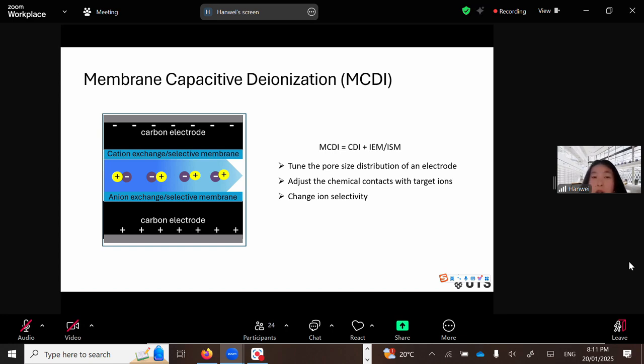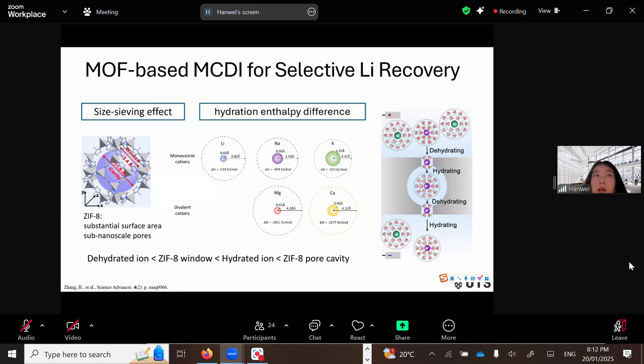So my PhD research on the MCDI cathode follows three directions to improve the lithium selectivity when recovering lithium from aqueous resources. The first one is I use a MOF-based material membrane on the activated carbon, based on the size sieving effect. I use a ZIF-8 based membrane on a commercial activated carbon electrode. ZIF-8 is a promising ion separation material. It's well known for its substantial surface area and sub-nanoscale pores. It is widely believed that it can achieve ion separation through a size sieving effect.